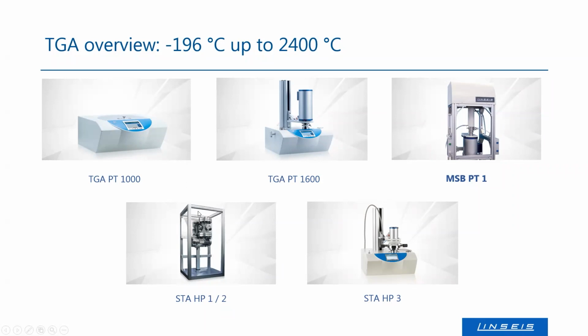And as I mentioned, all these instruments allow the use of many gases, but from time to time, you have the case that the customer has an application that needs and requires very corrosive gases, maybe even toxic gases, or the sample decomposes in something very corrosive, very toxic. It releases fluorine gases, halogen gas. It may release some sulfur, some phosphate, and so on, which could affect the balance and also is not good for the environment. And for that purpose, there's a special balance, the so-called magnetic suspension balance, the so-called MSB, which is a special shape and a special type of balance where you have a sample reaction chamber that's enclosed. There is no contact, no physical contact to the balance. It's an enclosed atmosphere, and that's why it's something very special.